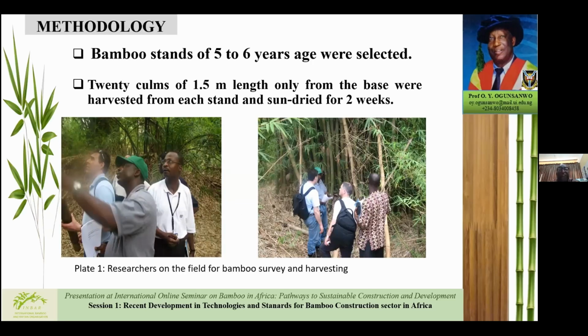On the basis of our findings, bamboo grows naturally here. And because people grow them in their farms and they occur naturally in farm fallows, we tried to find out the age of those because they are familiar with the ages. So 5 to 6 years old bamboo was selected. And then we took bamboo based on our preliminary study. We took 1.5 meters only from the base we harvested to ensure that we have enough thickness along the base to work with.